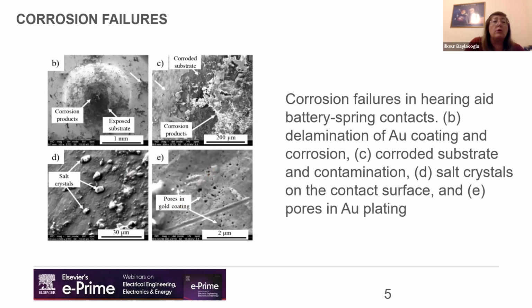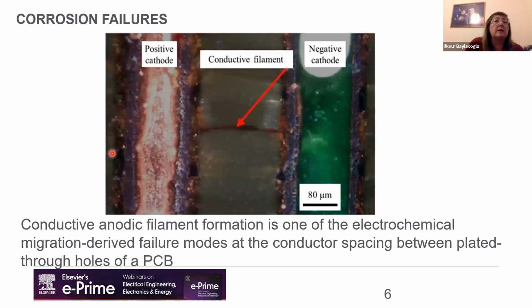And there is another corrosion type of failure, which is conductive anodic filament formation. It is an electrochemical migration derived failure mode. As it is seen here, this conductive filament is inside of the printed circuit board layers. It is not visible by naked eye, actually. And it is between the spacing between printed circuit board plated through holes. These are plated through holes, which components can be immersed in, or maybe they are just via holes.